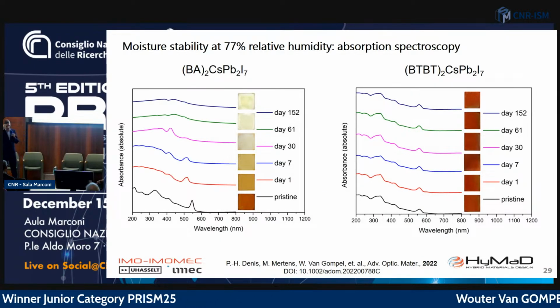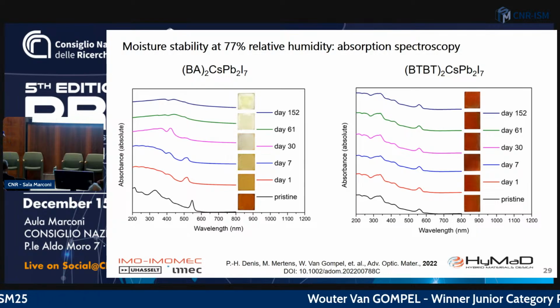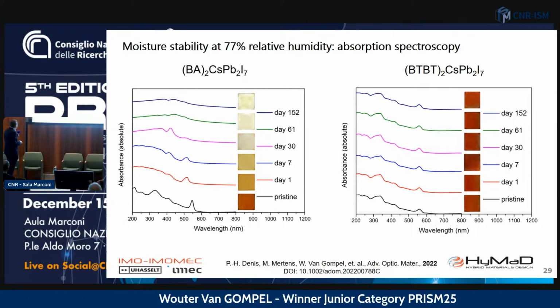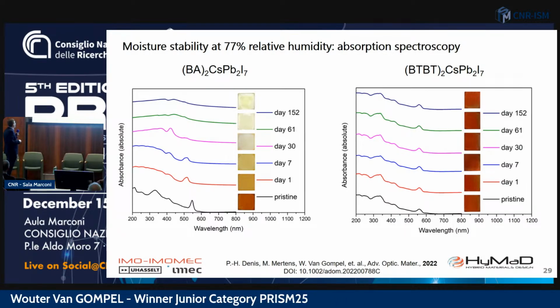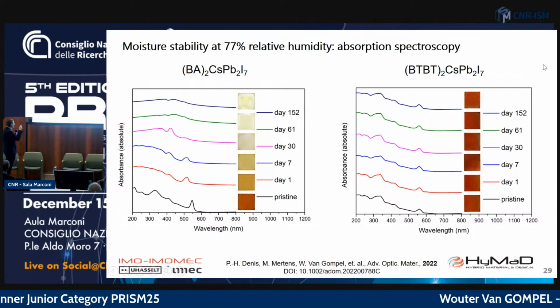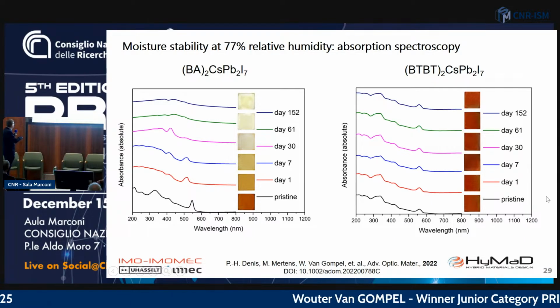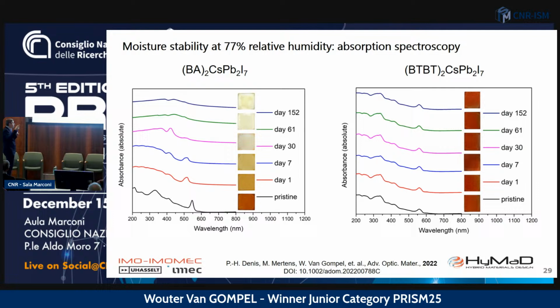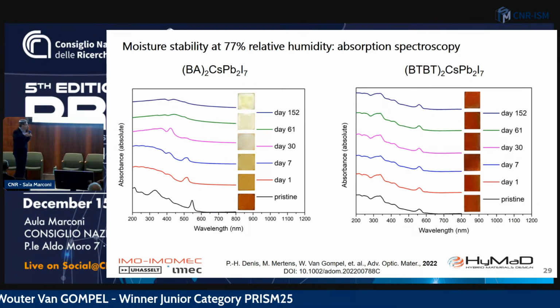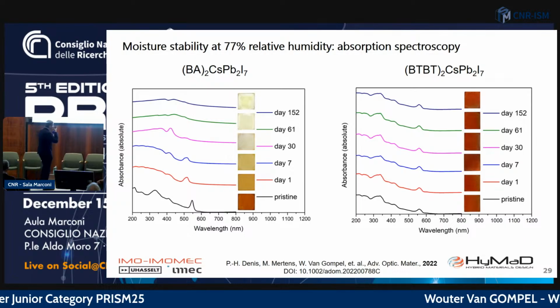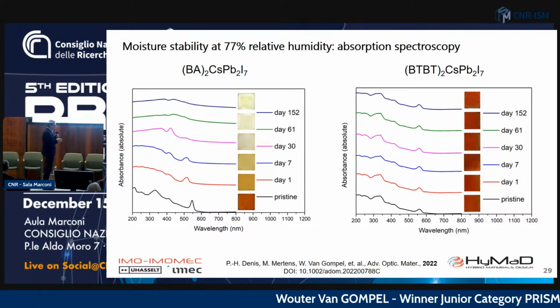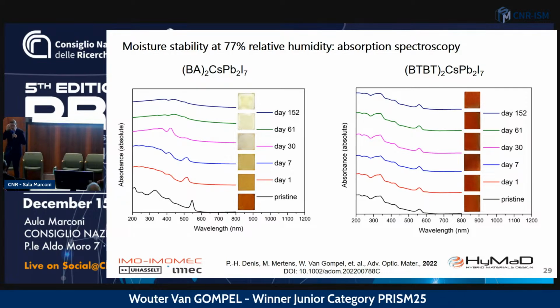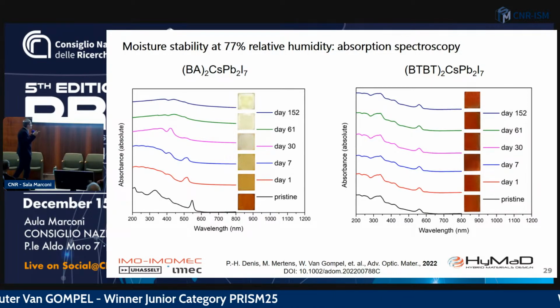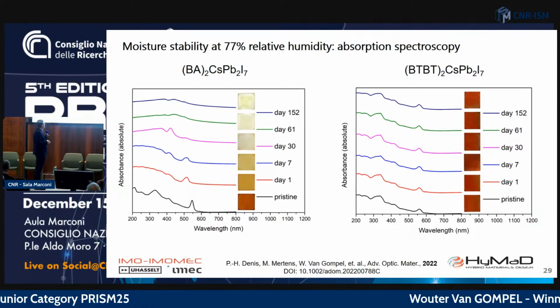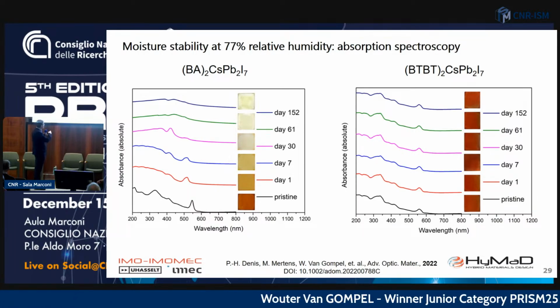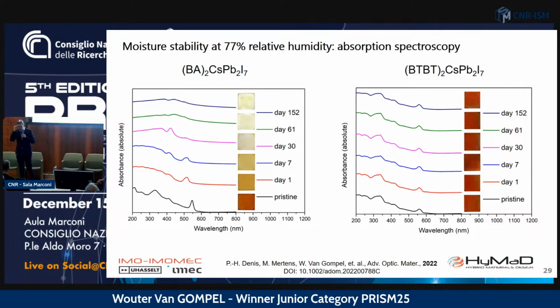So going directly to the interesting part, if you put these 2 films in a desiccator at a very high relative humidity, 77%, so quite harsh conditions, then you see that the reference starts to degrade already after 1 day from the n=2 to the n=1, and then over time it completely degrades into a hydrate phase and lead iodide, which is a very typical behavior for these perovskites. While the one with the BTBT remained stable for more than 152 days. That's just when we stopped for this study, because you can keep on going, of course. But after the study, we kept it in this environment for more than a year, and it's still unchanged in absorption spectroscopy. So just changing the organic makes a huge difference in the stability of these materials.